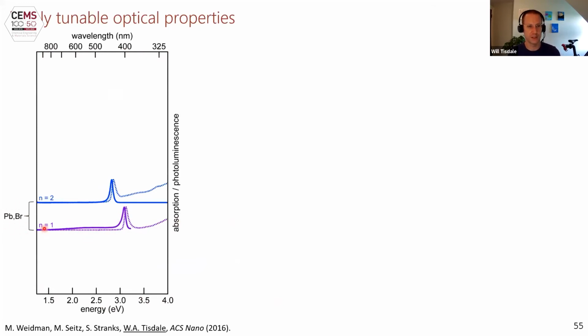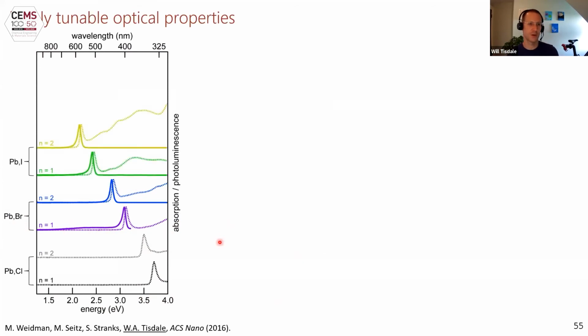For the lead bromide system, looking at just the two thinnest members of this family, the N equals 1 and the N equals 2. N equals 1 is right on the edge of the ultraviolet. The N equals 2 is a nice deep blue. If you go up on the periodic table from bromide to chloride, we can push the absorption into the ultraviolet. If you go the other direction, down on the periodic table from bromide to iodide, the emission spectrum moves from the green to the yellow. And if you substitute lead for tin, you can get orange and red emitting nanoplatelets as well.